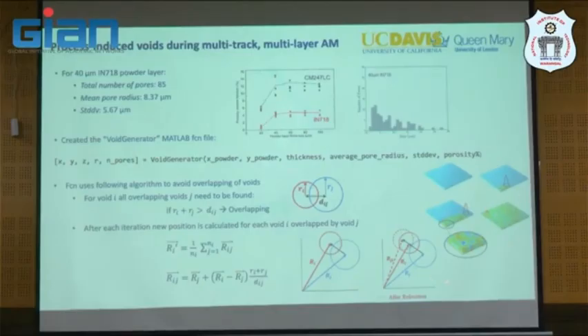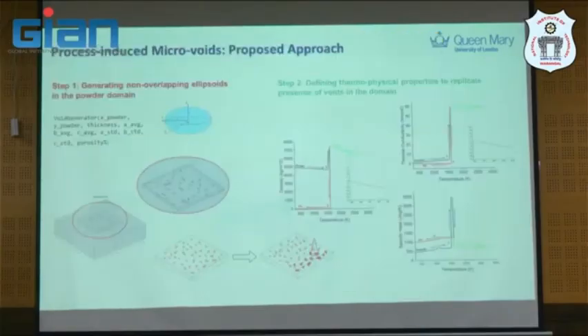For example, this is a conceptual idea. The color bar here shows red means more porosity. So somehow this will impact your residual stress and some other properties. So this is probably the first step. We define the defect based on the data from a lower length scale model or experiment, and then identify the thermophysical property that replicates the presence of this defect. In this case, it's a void, a small pore.